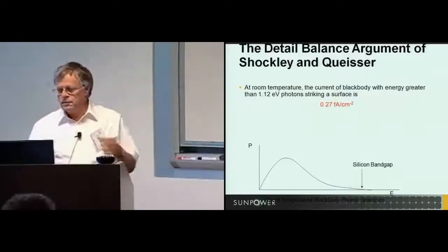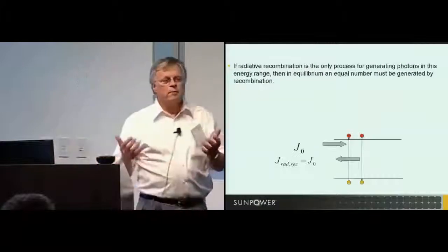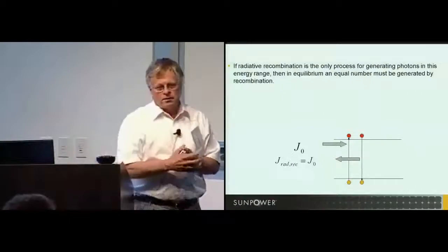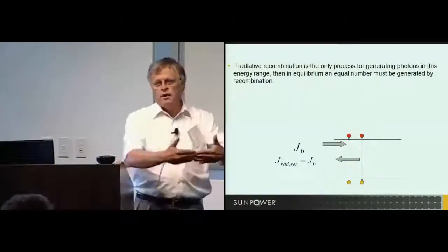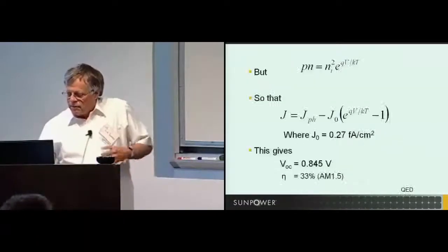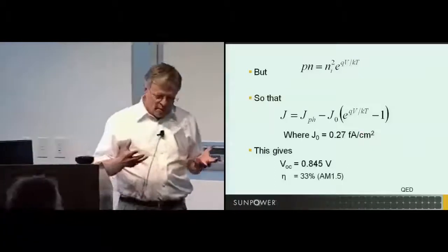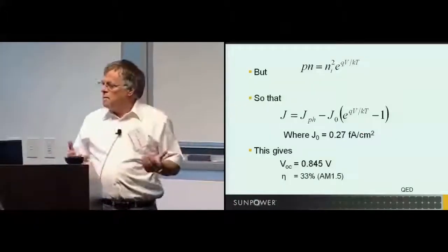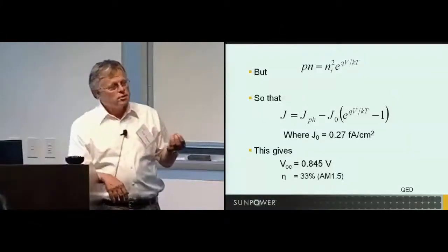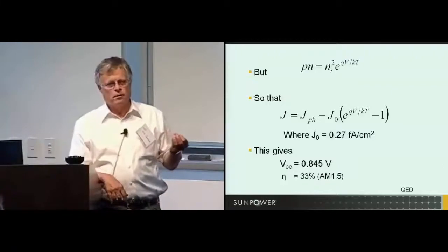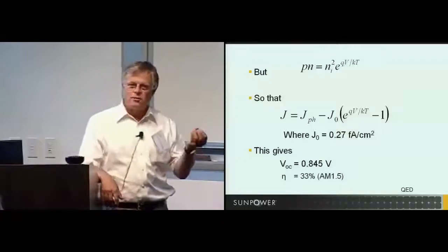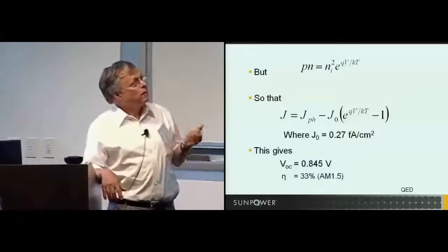And so he's saying, well, gee, in equilibrium, when the cells recombine, everything should be in steady state, so it should be emitting the same amount of radiation back to the blackbody surroundings. And I won't go through the math here, except very rapidly you get sort of a standard diode equation. The main point being that the recombination of electron holes is proportional to the PN product. And that's really where the factor of 2 comes in. If you do it for the N product, it's 2, and for the PN product, it's 1 in kT over q.